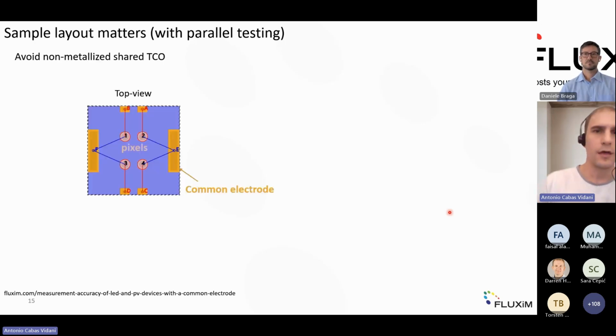Now, we covered a lot, and I mentioned multiple times the importance of parallel testing, but I would like to leave you with one last observation that comes directly from our laboratories and together with our customers, which is the sample layout. In case of parallel testing, it actually matters quite a bit. And it matters especially if you have a pre-structured TCO. This is often a choice for lab-scale devices, where laboratories get a pre-structured substrate with a TCO on top. And the TCO acts as an electrode for your pixels. You see here a schematic top view of a sample with a common electrode, so one electrode that connects to 2 pixels.